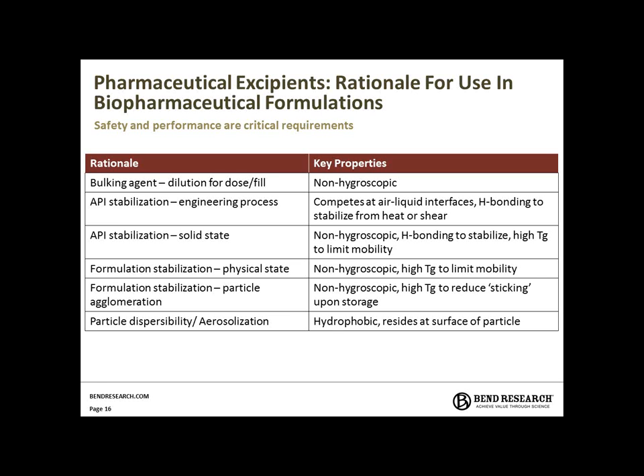On this slide, we have a number of reasons why someone may or may not use an excipient. The first few reasons are bulking and API stabilization, from the engineering process state as well as the solid state. We also need to stabilize the particles themselves. We often use non-hygroscopic, high Tg excipients to limit mobility of the molecules in the formulation in relation to each other, and also in relation to the API itself, which would create a long-term stable formulation. We also want to mitigate particle agglomeration and reduce sticking upon storage.